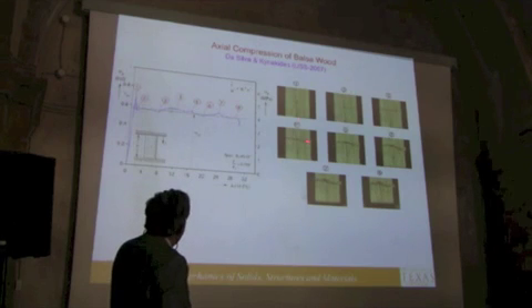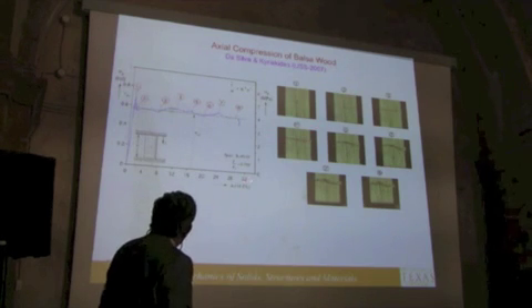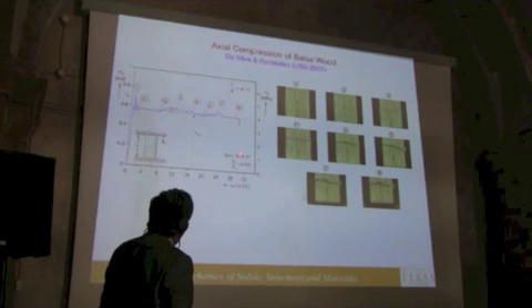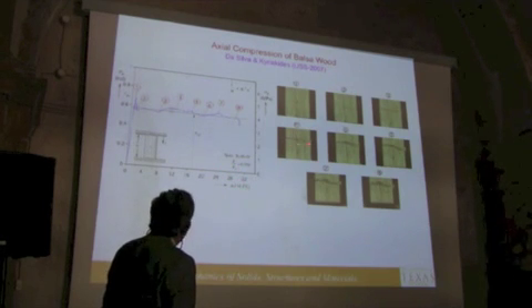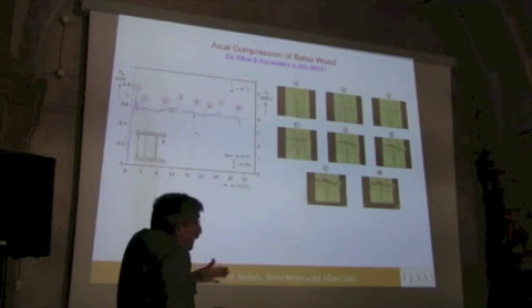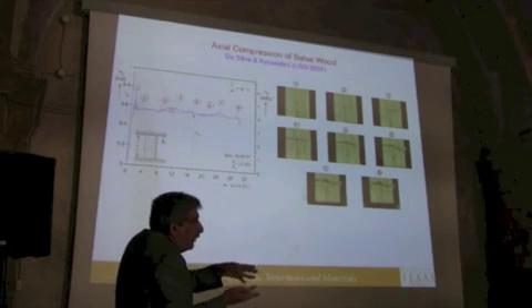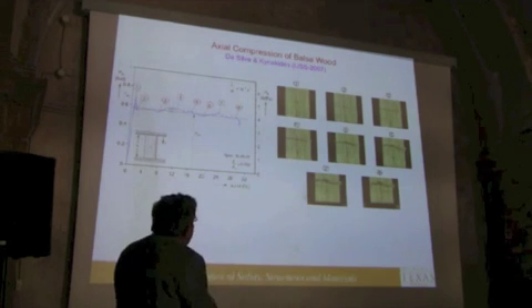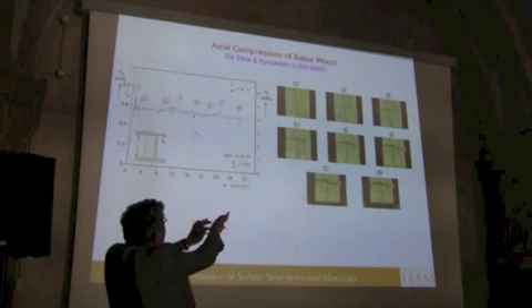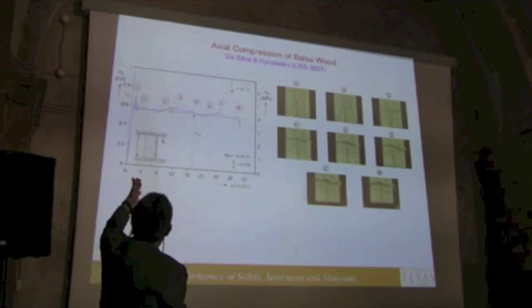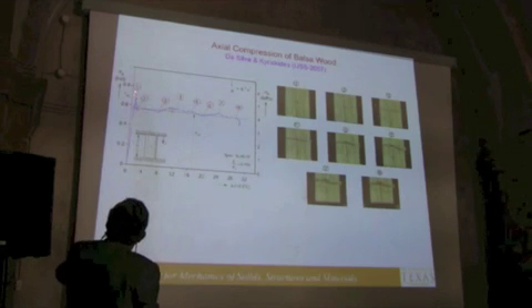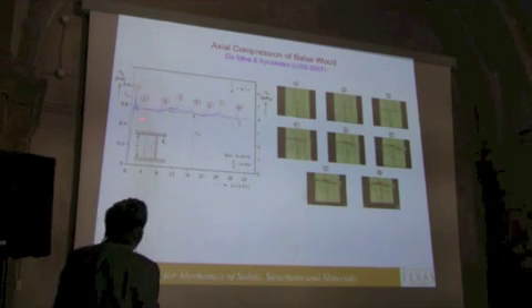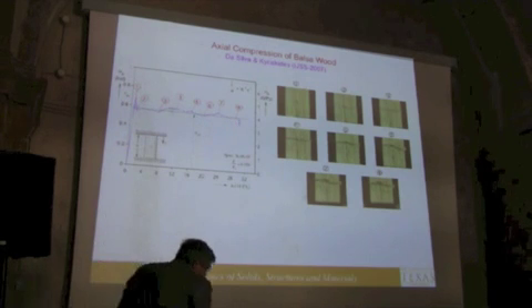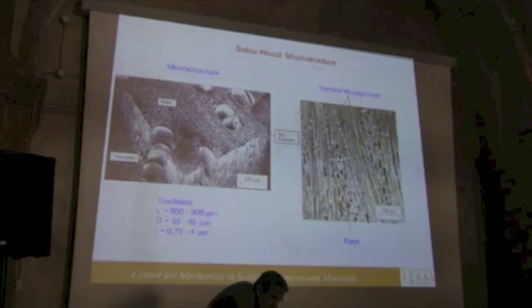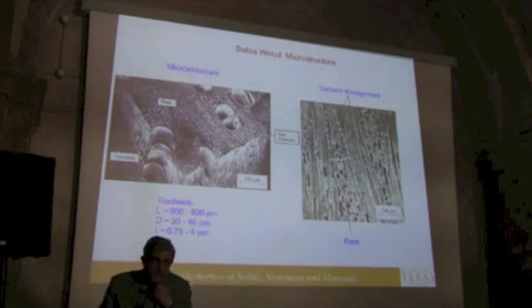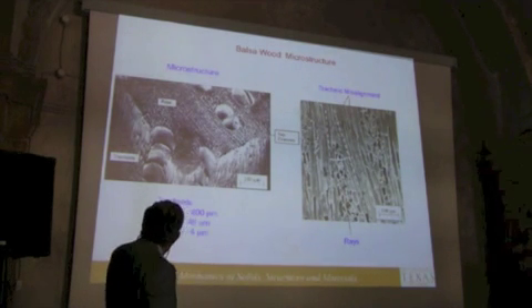Okay, and what happens is that by the time we have come here, we reduce the height by 30%, and it looks like not very much has happened. It's because that little bit of material that's there has been highly compacted, and there's just been a few splinters coming out of the specimen. But the key here is this instability that is occurring here, and then the extended plateau. The behavior is similar. I don't have analysis for this problem. I just have a few things.